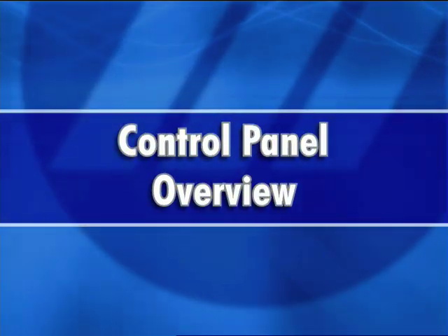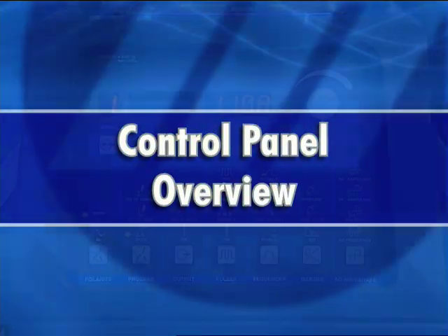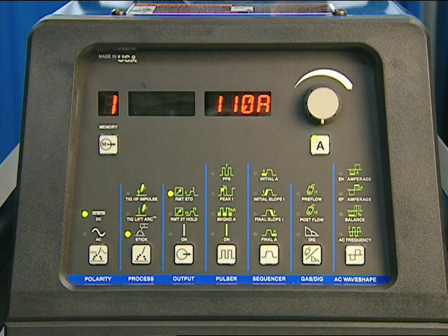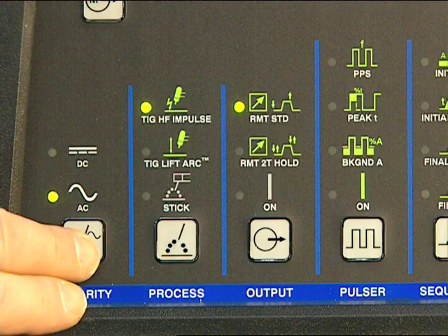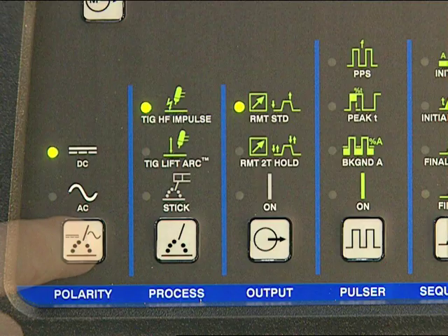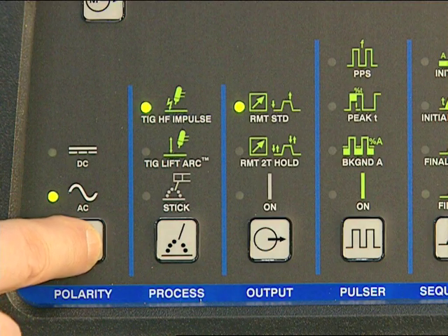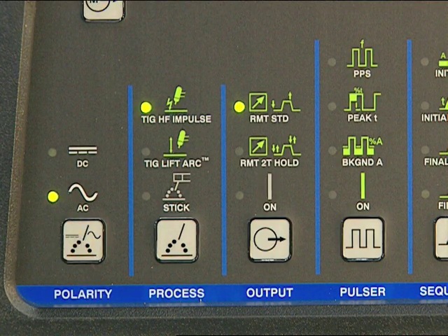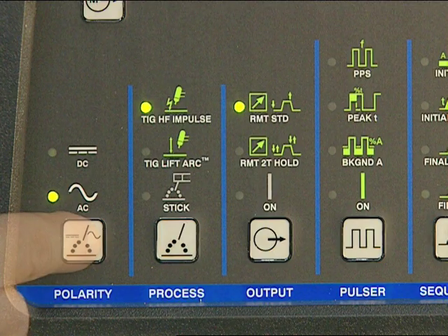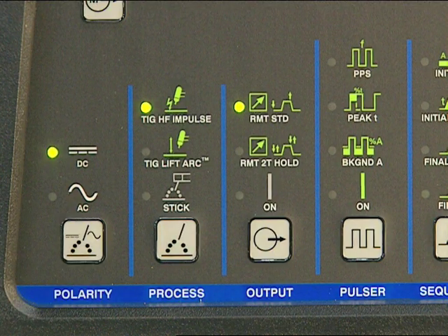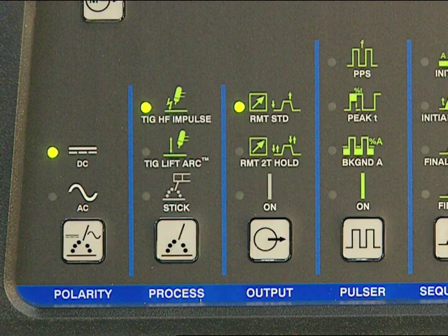Now let's take a look at the control panel. You can set the polarity by choosing AC or DC. AC polarity is typically used for welding aluminum and similar alloys in the TIG process. DC is used for TIG welding mild steel, stainless steel, copper, titanium, and nickel alloys with the TIG process.